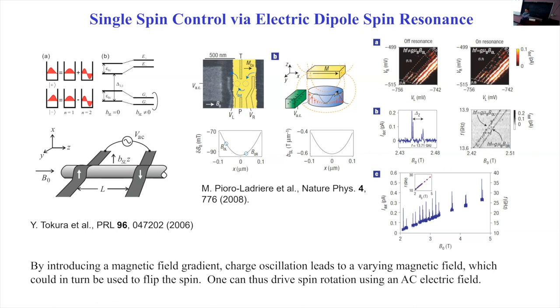But if you want to use an electric field to drive a magnetic moment, you need something to connect them. So naturally, you would say, oh, use spin orbit interaction. Turns out, as I mentioned, silicon and gallium arsenide are both light elements. The spin orbit interaction is not very strong. But in 2006, I believe, and then experimentally demonstrated in 2008, people came up with the idea of introducing an artificial spin orbit interaction by introducing a magnetic field gradient in the cell. When you do that, if you have an electric field shake the electron in that field gradient, you can imagine that from the electron rest frame, you now actually have an AC magnetic field, right? And that AC magnetic field then drives the spin transition. And so that becomes, especially in silicon, the most dominant single spin rotation technique by now.